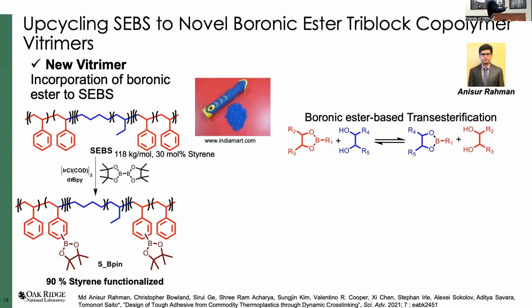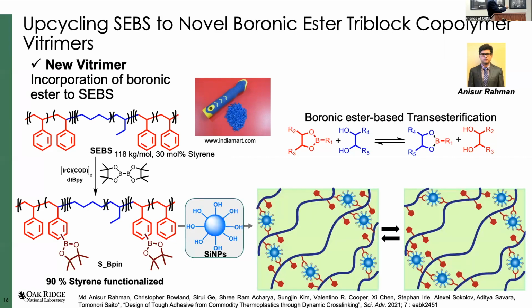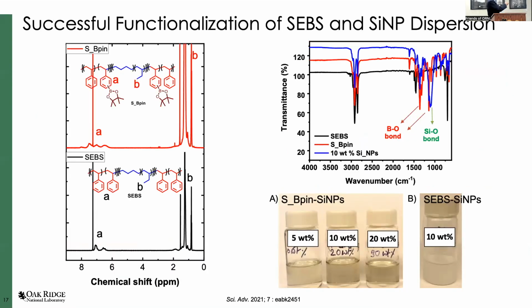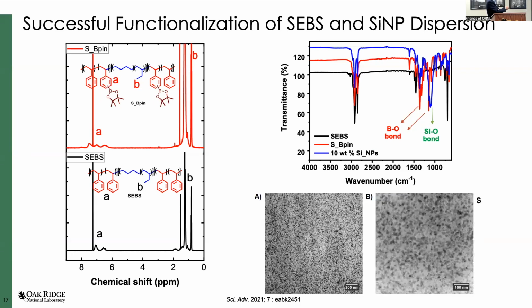What we found out is that the initial expectation was to cross-link with this, but we can cross-link with silicon nanoparticles. So through this boron ester exchange, you can make a bridge. That makes a very useful material. I'm going to go into a little more detail. These are some evidence from NMR showing this change, and IR showing the change. But I'd like to show one thing. This picture is a little dark, but on the right-hand side, this is not functionalized. So starting material with silicon nanoparticles doesn't disperse that well. They don't like each other. But once you functionalize, it has interactions, and once it dries, it's nicely dispersed silicon nanoparticle.